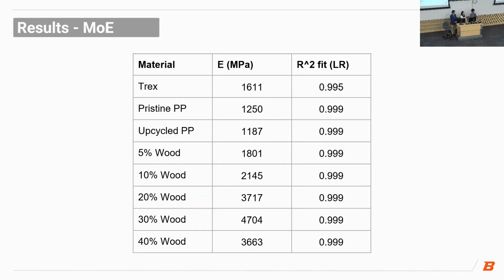There are two data points. One is the actual modulus of elasticity that was calculated for these materials, and the other one is the least squares fit to make sure that we are fitting the linear elastic region of the stress strain curves as best as possible, and that'll be explained later. But here we see that Trex exhibits about 1600 megapascals. Pristine and upcycled polypropylene have around the same modulus of elasticity as well, around 1200 megapascals.